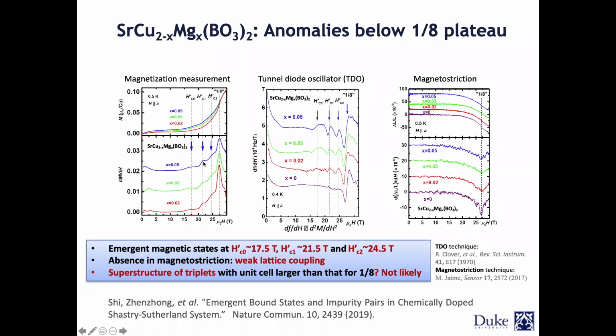Then we said, okay, let's focus on this and see what's going on here. Did we really have enough concentration to push this into some new state? This is the derivative of the frequency, df, from the TDO measurement again, taken so that it would be easier to see. You can see that in the pure case, there's nothing going on. At 2%, these anomalies start to show up.